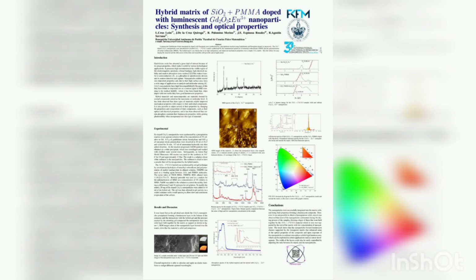Also, since the stages of the sol-gel process are slow, it is possible to add doping agents, in this case the nanoparticles, so that they remain encapsulated due to the aging time and the subsequent evaporation of all the solvents. Once the gel is dry, the result is a small tablet that precipitates the nanoparticles on one of its faces and presents a good luminescence under UV excitation.